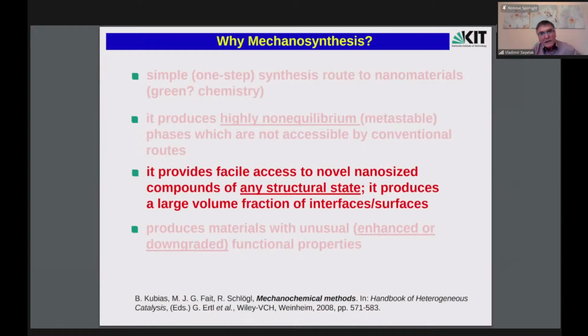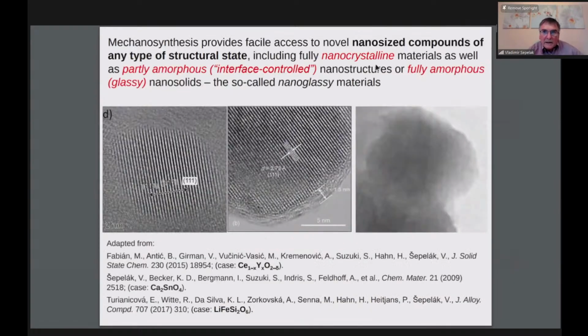Why mechanosynthesis? The third point which I would like to mention is that mechanochemical synthesis provides access to novel nanosized compounds of any structural type. It produces a large volume fraction of interfaces and surfaces, as is demonstrated here. Using this mechanochemical route we can obtain novel nanosized compounds of any type of structural state, including fully nanocrystalline material, as well as partly amorphous, sometimes called interface-controlled nanostructure, or fully amorphous glassy nanosolids, the so-called nanoglassy materials.